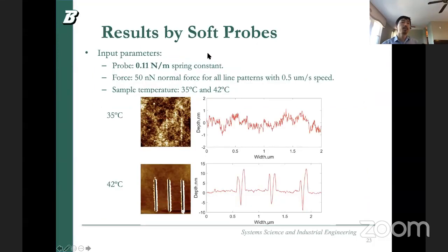So for the input parameters, when we use a probe with a very small spring constant, a soft probe, we can use a 50 nanonewton normal force. As you may notice, 50 nanonewton is a very, very small force that almost cannot be implemented by any other AFM-based nanomachining techniques. To our best knowledge, we can do this even at 50 nanonewton, and we can also do it at about 10 nanonewton if we use the stiff constant. So this is our advance in this AFM-based process.